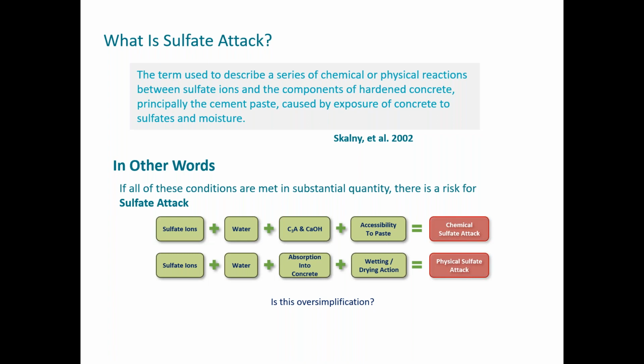And the first complication that I ran into is that sulfate attack is widely split into two main categories, one being a chemical attack and the other being a physical attack. And so I decided I was going to create two separate equations. Basically, in order for a chemical sulfate attack to occur, you have to have sulfate ions, you have to have water, you have to have C3A and free lime, and they have to have accessibility to the paste. They have to be able to enter into the concrete, into the paste matrix. And that is essentially my oversimplified definition of chemical attack.